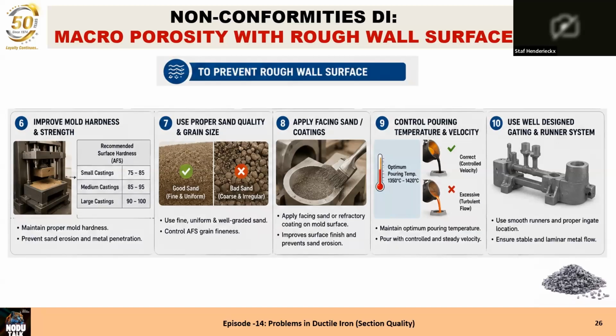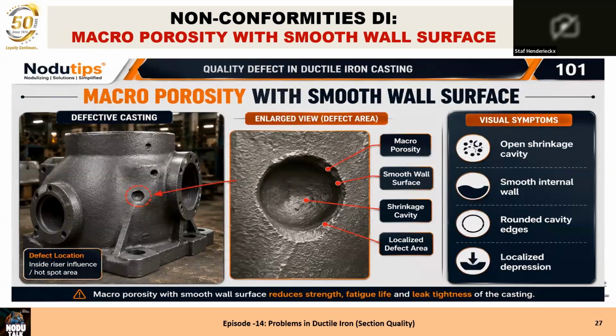Again, pouring temperature and the pouring velocity. Pouring velocity matters because when you have too high metal speed, it can remove some sand and you can have a problem. Again, a well-designed gating and runner system. If we see here the defective casting, it can be inside, under the riser, it can be in a hot spot. Wherever, we see here in the middle picture the macroporosity with smooth walls. It's a shrinkage and it can be open and so on. When does it appear? We can see it in the next slide.